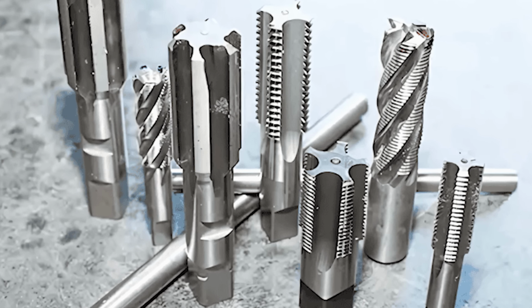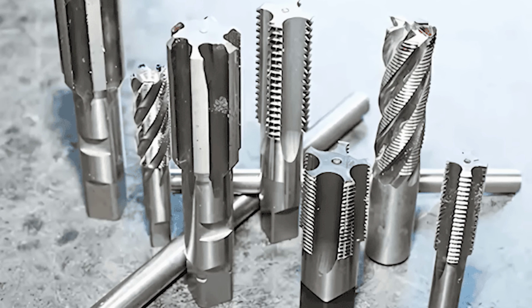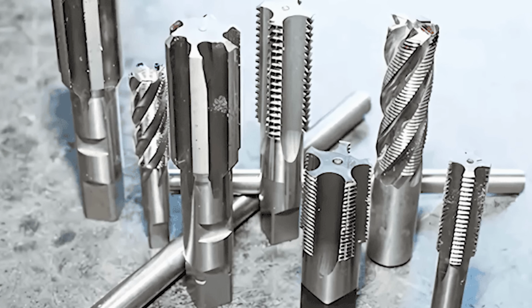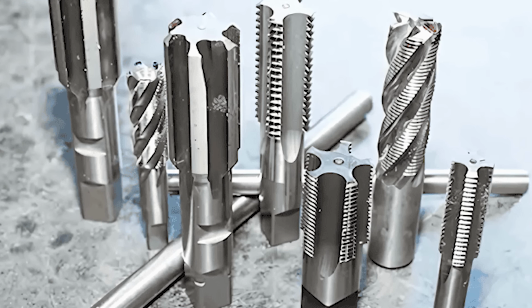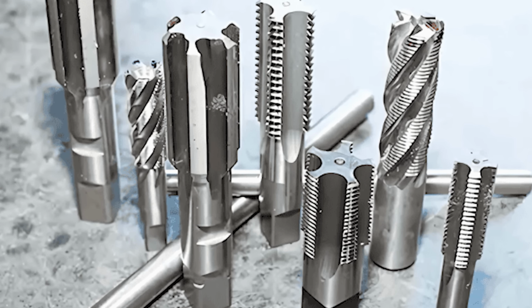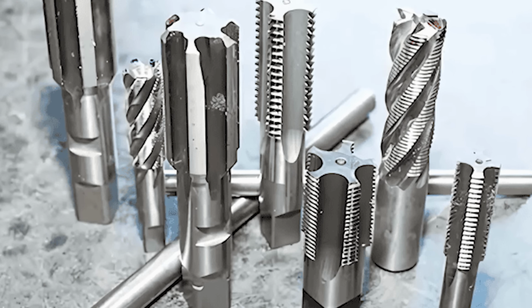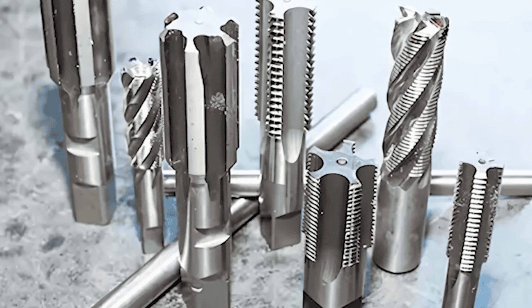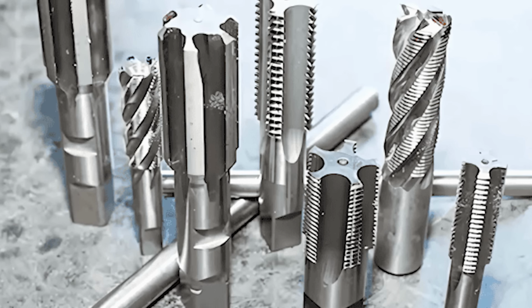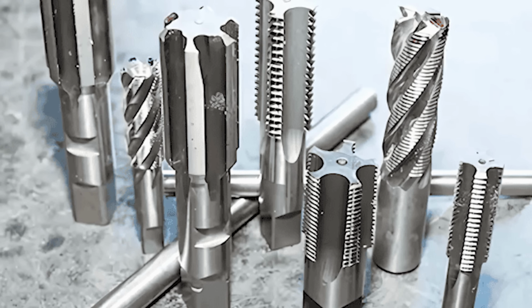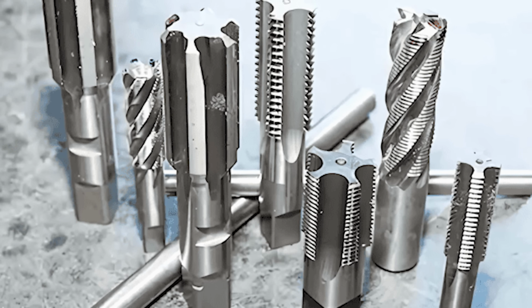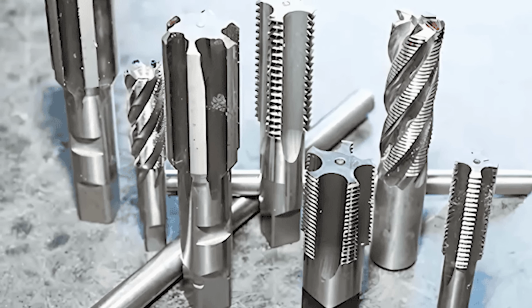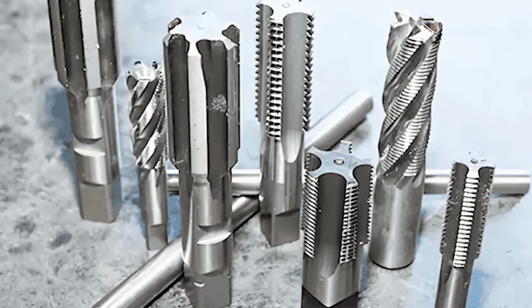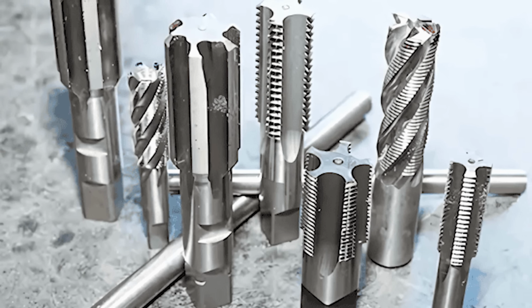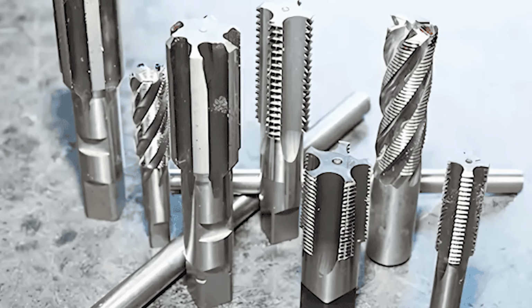White's laboratory notebooks from this period read like a metallurgical exploration of uncharted territory. Batch number 217, tungsten increased to 8%, heating to 1900 degrees, air cooling. Result, excessive grain growth, brittle failure. Batch number 218, same composition, furnace cooling instead of air cooling. Result, acceptable hardness, edge retention, poor. Each entry represented hours of preparation, careful temperature control, and detailed analysis of the failed results.